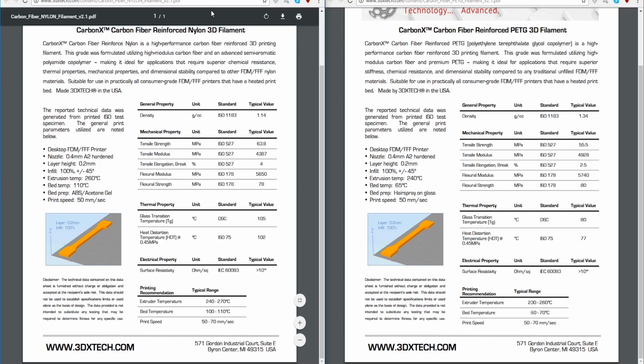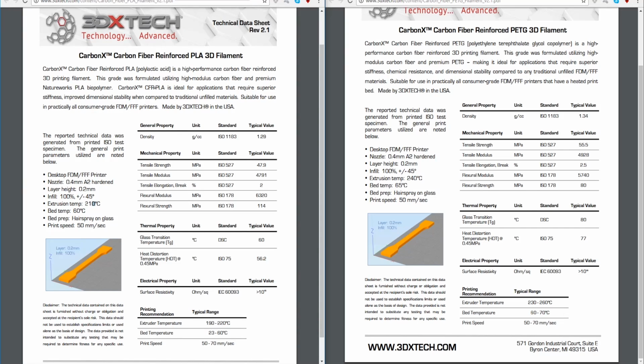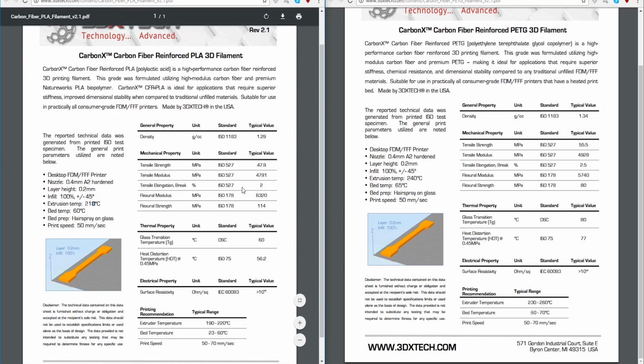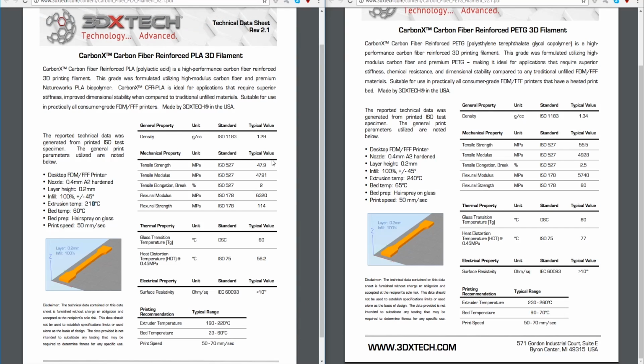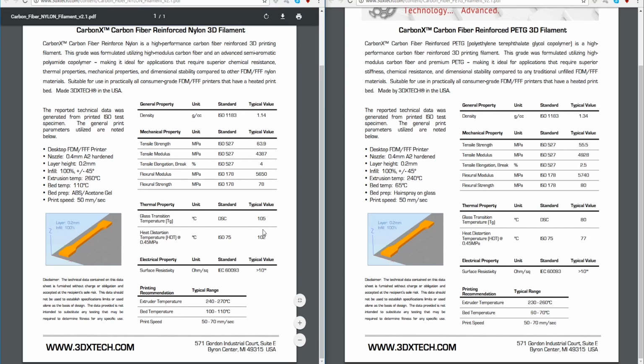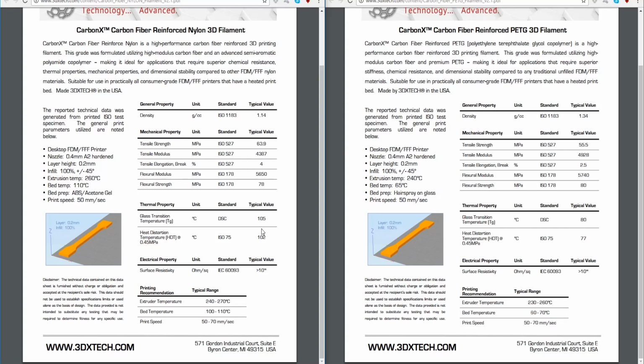So it looks like here in the combination of my picks, the best ones are probably PLA. PLA for ultimate stiffness, so ultimate strength if you have no heat load, but your design you're trying to minimize flex. Nylon is going to be your all around, good strength, not as good as PLA, good heat and temperature resistance, and maintains its stability. Also very tough, it will flex a long way, so if something happens and your machine gets beat on or whatever, it'll stretch twice as far before breaking, so that you could later see the bend in that part and replace that part without it failing.